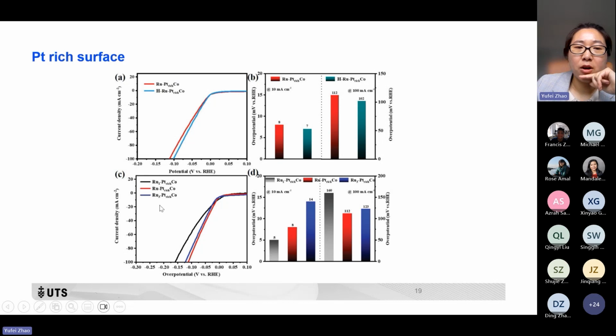Also, we have changed the content of the ruthenium to investigate the role of ruthenium in the performance of the alkaline HER. For the ruthenium content here, we found that if we lower or increase the ruthenium content, the performance changes a little bit, but not that much. So the ruthenium may also contribute a lot to this alkaline HER process.